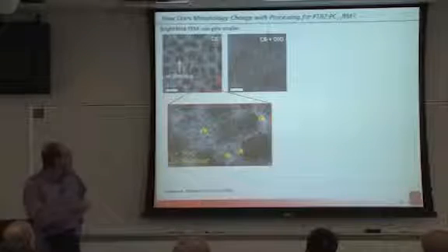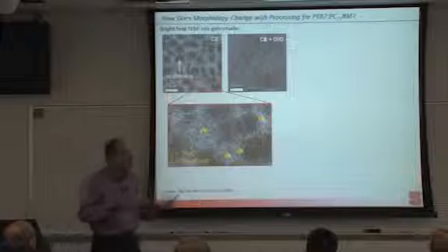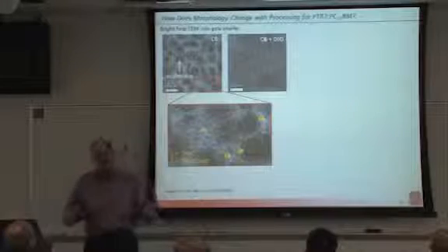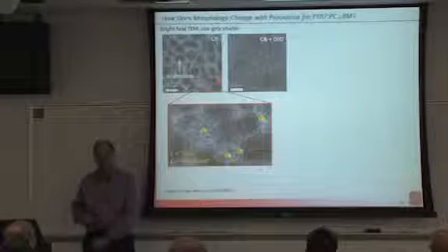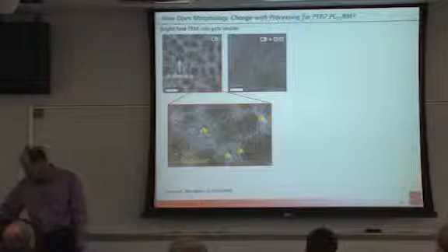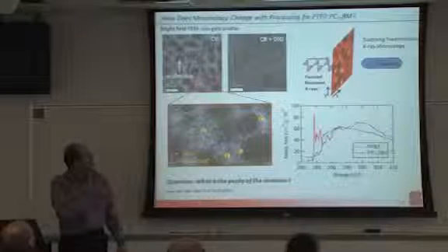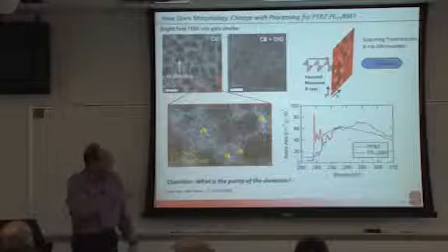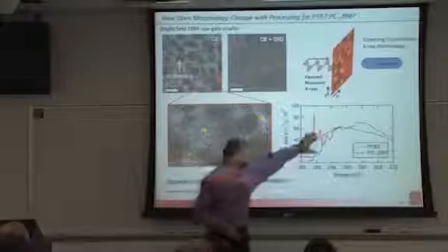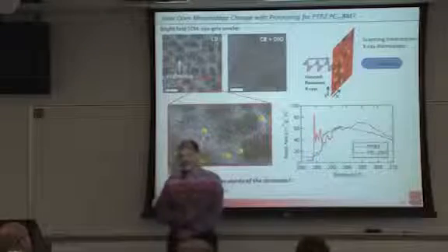And besides that, this is bright field TEM, so I don't really have a quantitative measure for the purity, so I don't know how pure these domains are. Those are the things one would like to know, and we will use X-ray microscopy and scattering. Here are the differences in the spectra. They're very large, so I can use that to give me quantitative compositional analysis.